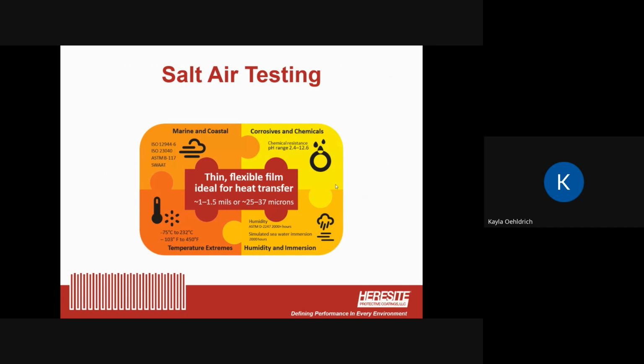So let's talk about really the most popular environment that our coatings are used in to protect a coil, and that's the salt air environment. Our products are selected for both coastal and offshore marine environments. So this involves really environments that have different temperatures, humidities, dryness, and in various parts of the world. So, for instance, the Space Coast in Florida and the US is a particularly difficult environment because of the salt air concentration and the humidity. Dubai in the UAE has a very salty environment, but it has very dry air with humidity at night.